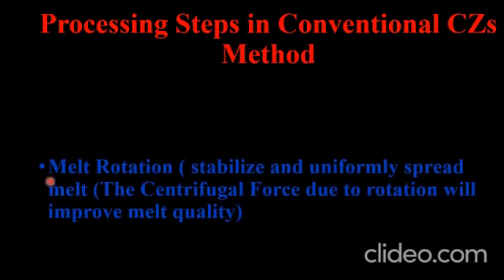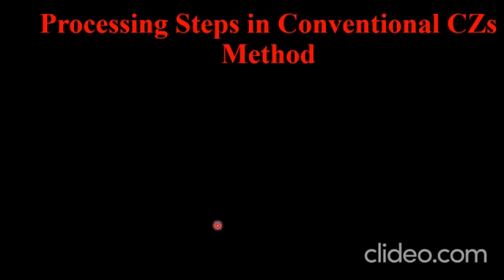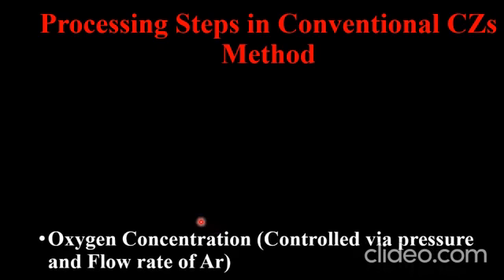Dear student, you should know that the melting material has different viscosity at different points. In order to get uniform melt material, the melt is rotated. The centrifugal force of the rotation spreads the material uniformly, and in this way the quality of the melt material is improved. Next, the oxygen concentration is very important in the Czochralski method, and this concentration is controlled inside the chamber by controlling the pressure and flow rate of the argon inside the Czochralski operating setup.